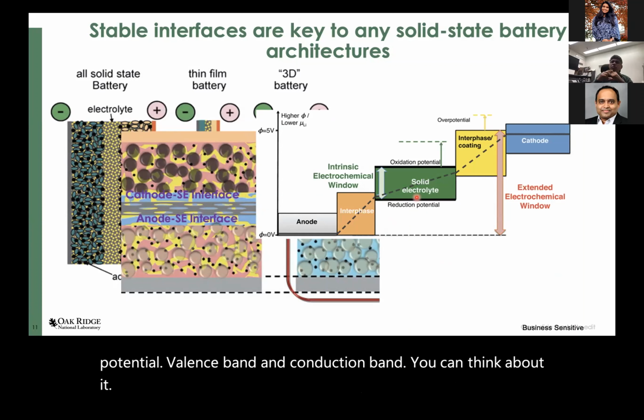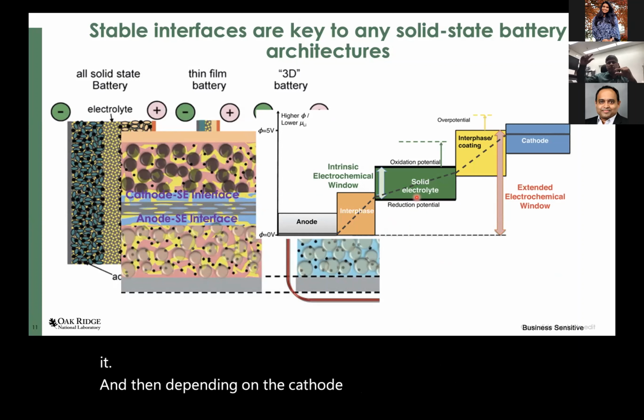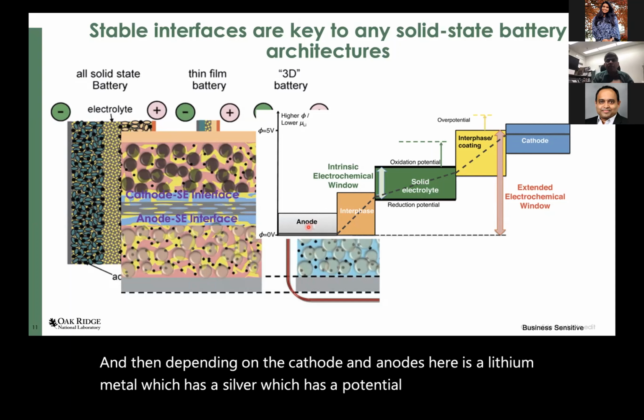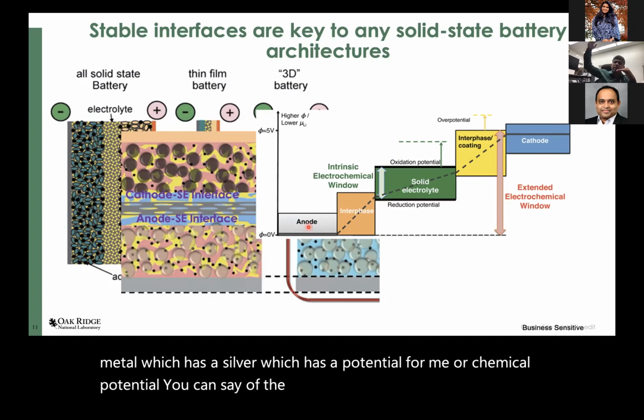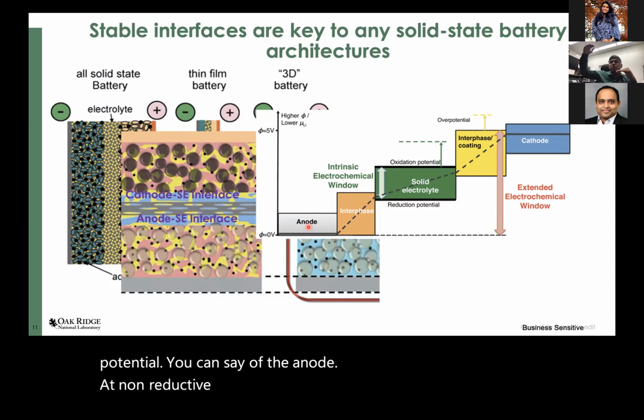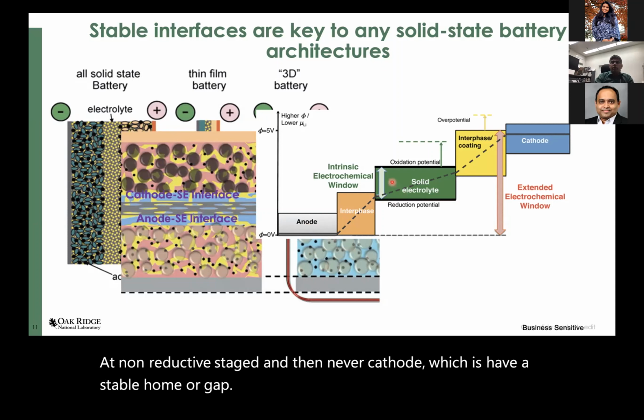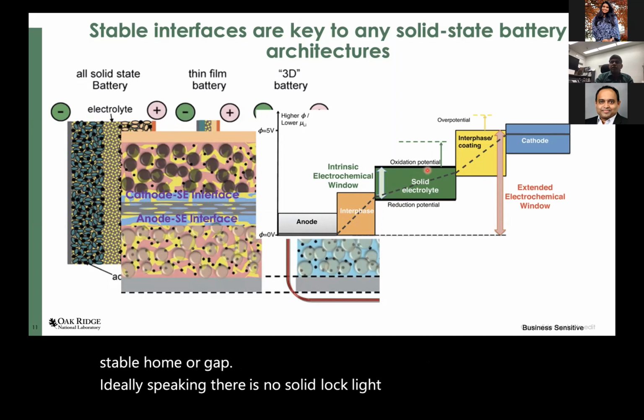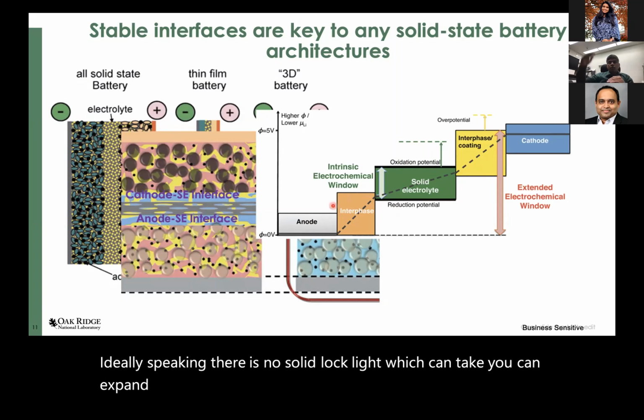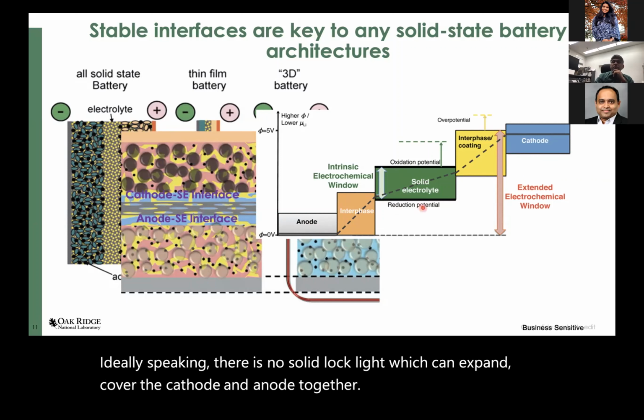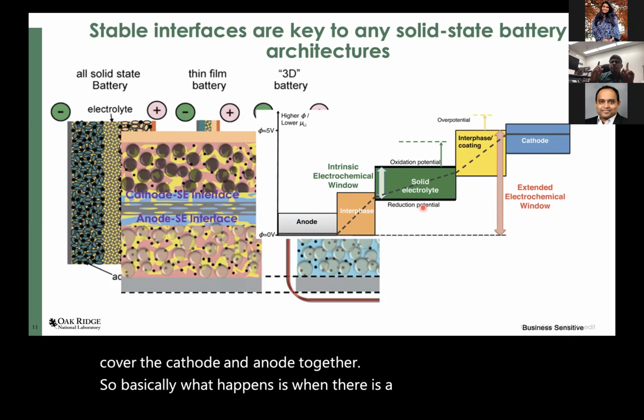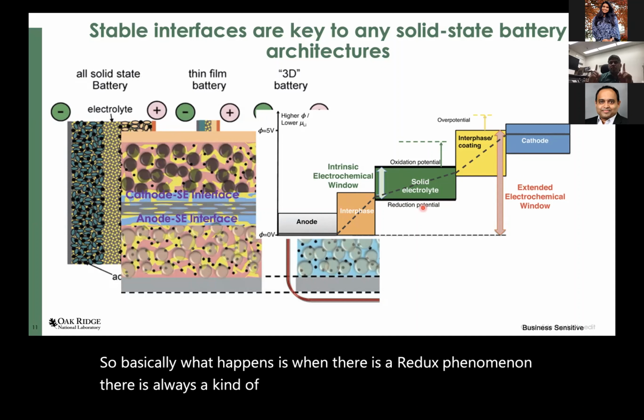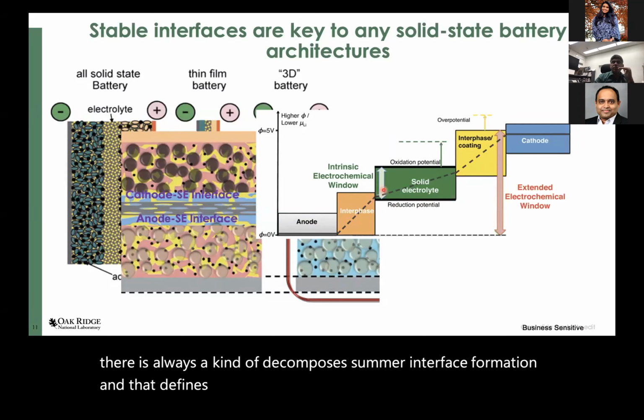And then depending on the cathode and the anodes, here is a lithium metal, which has a Fermi or chemical potential, you can say, of the anode at non-reductive stage. And then we have a cathode, which has a stable HOMO-LUMO gap. Ideally speaking, there is no solid electrolyte which you can expand to cover the cathode and anode together. So basically what happens is, when there is a redox phenomenon, there is always a kind of decomposition or interface formation, and that defines the effective chemical potential.